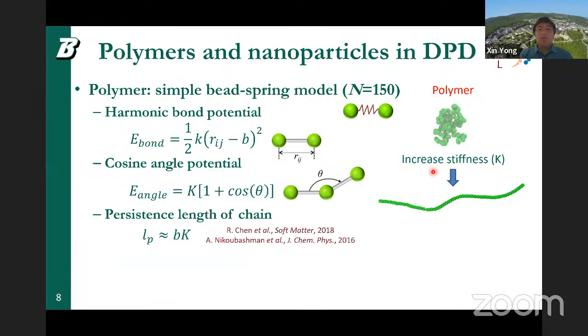So in order to model polymers and nanoparticles in DPD, we adopt very basic, simple models for the polymers. We just use a simple bead-spring model with a harmonic bond potential and a cosine angle potential. The bond potential controls the connectivity, while the angle potential tunes the rigidity of the chain. By simply increasing K, we can vary the polymer conformation from a globular, coil-type polymer to a very stiff chain. And K can also be related to the persistence length of the chain, which gives us a more physical relation between a simulation parameter and a physical property of the chain.